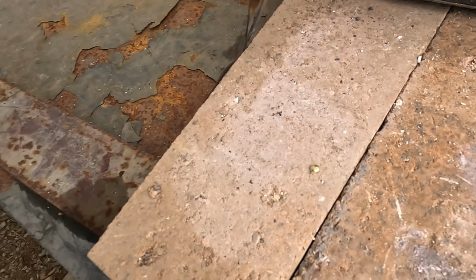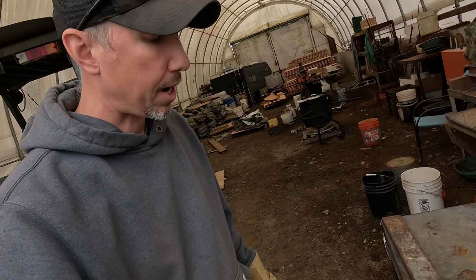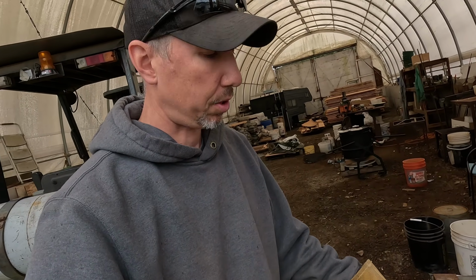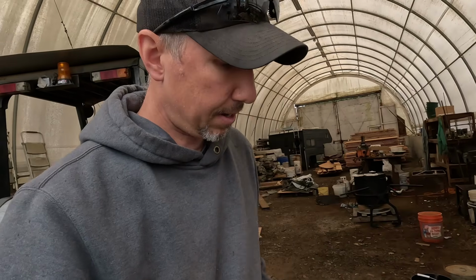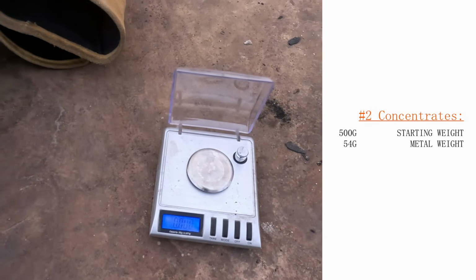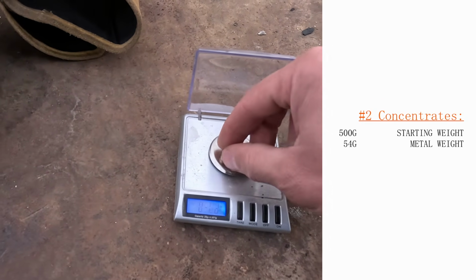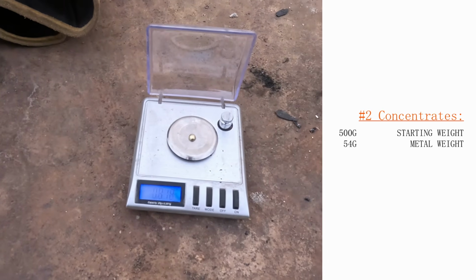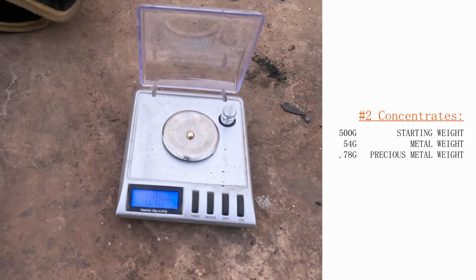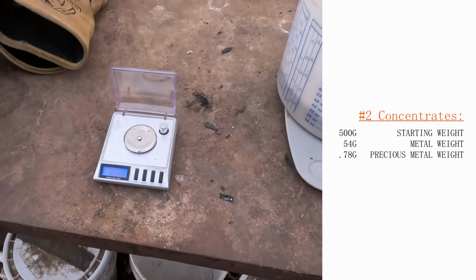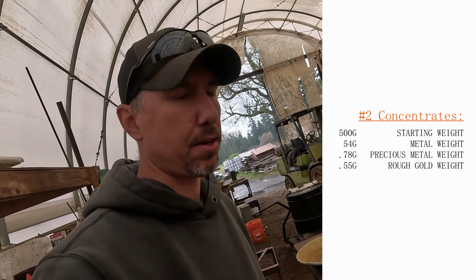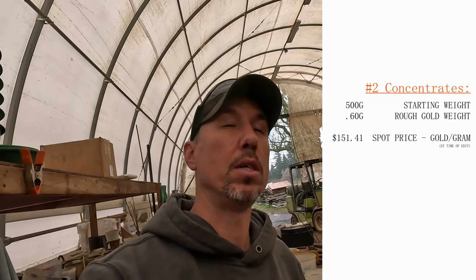Let's go get it weighed. It's really yellow. It's really nice and yellow, which is surprising because on the previous video, it was about 60-40, 65-35 gold to silver. This looks like it's more like 80% plus. So let's have a look here. Okay, here we go. It's 3/4 grams. So there's probably roughly 0.6 grams of gold in there, which is about $90 at today's price.